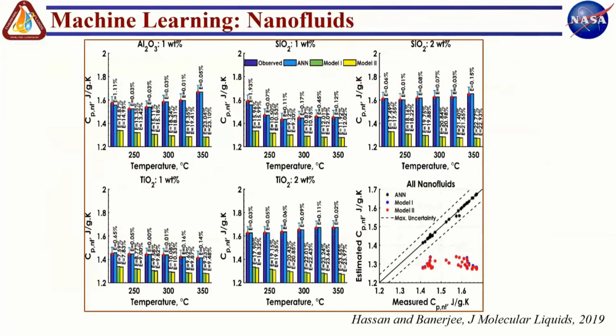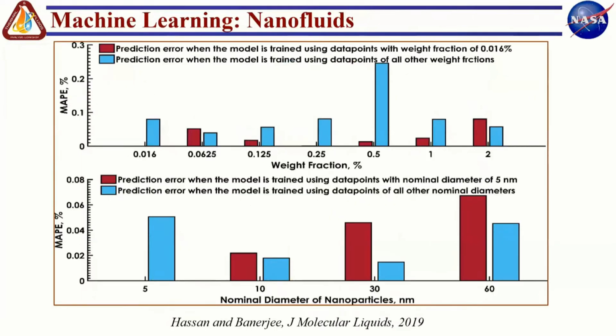And so this one shows the different errors that we got using a whole bunch of different types of NN models. We tested out different types of optimization procedures. And what we found was, depending on how you do the training, you can end up with different levels of error. But the take-home message is, using this technique, we were able to do predictions with errors of less than 0.1% in the prediction of the heat capacity properties of these molten salt nanofluids.